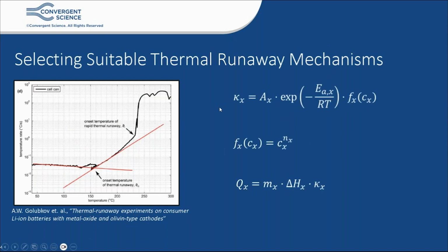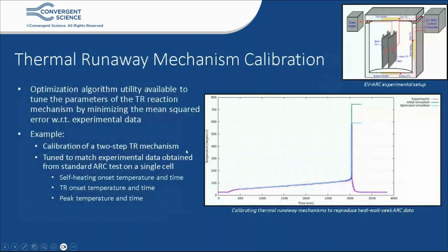To calibrate a thermal runaway mechanism, we go back to the reaction rate formats and try to optimize or tune the values of the pre-exponential factor, the activation energy, the reaction order, and the reaction enthalpy. In order to aid users in calibrating their thermal runaway reaction mechanisms and all the associated parameters, we have developed an optimization algorithm utility that allows you to tune those reaction kinetic parameters and minimize the error between your simulation predictions and your experiments. Here we obtained experimental data for a heat-wait-seek type ARC, and then we calibrated a 2-step thermal runaway reaction mechanism. The original mechanism, shown in green, was over-predicting thermal runaway behavior, but once it was optimized, it was able to accurately reproduce experimental thermal runaway characteristics.